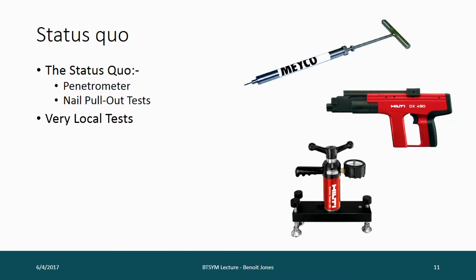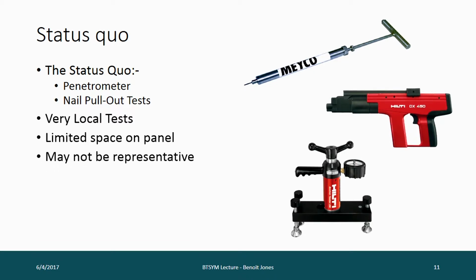And also, you're relying on the engineer doing the tests and reporting them accurately. There's also limited space on a panel, depending on the size of your panel, so you can't just keep doing these tests. And the Hilti pull-out test, to fire 10 nails and pull them all out, takes like 15 minutes at least. So you can't just be continually doing these till you get to the strength you need. You have to make decisions about how long to wait, how often to do them. And they might not be representative of the lining itself.